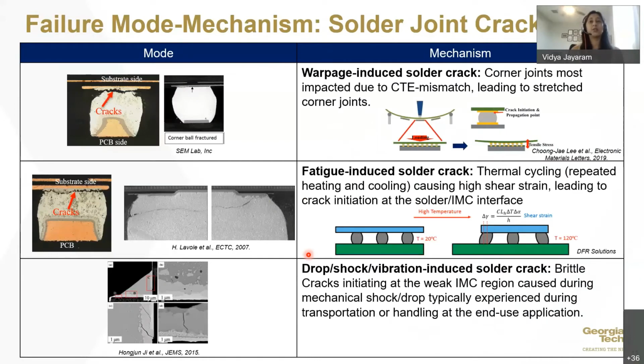Another type of failure is solder joint cracking. You can see images here of, again, similar types of failure that are induced by different mechanisms. Looking at a process level mechanism, which could be warpage induced, this warpage is typically caused by CTE mismatch. You have a silicon chip that is assembled on, let's say, an organic high CTE substrate. Because of the high CTE mismatch, you would see either a smile shaped or a frown shaped warpage, and that can lead to tensile stress. For example, where you have a smile shaped warpage, you can have tensile stress at the corner bumps, and that tensile stress can then lead to solder joint cracking.